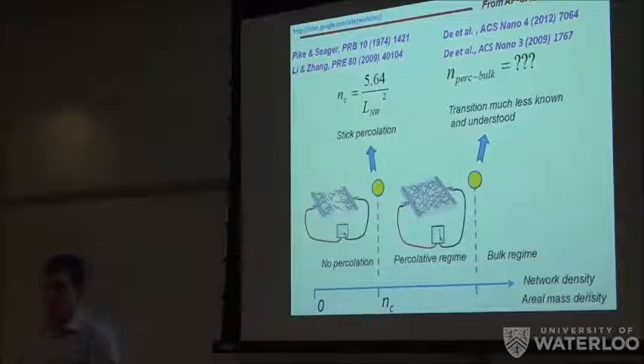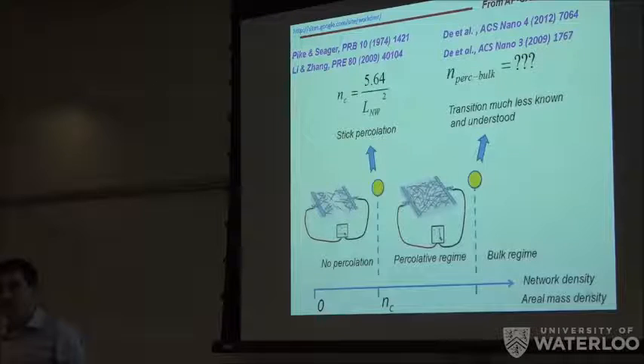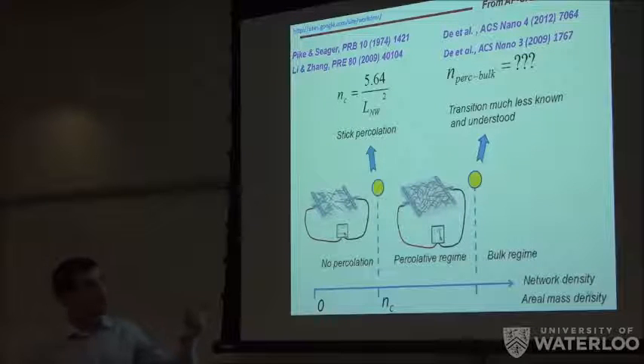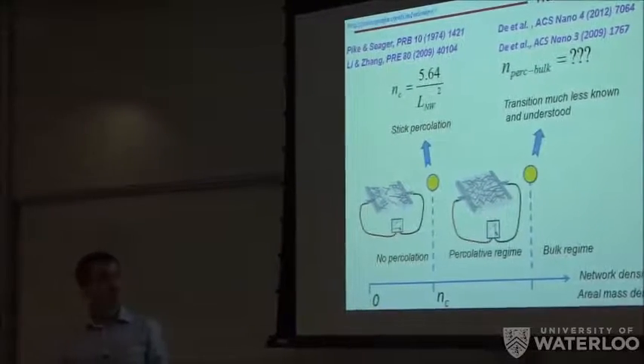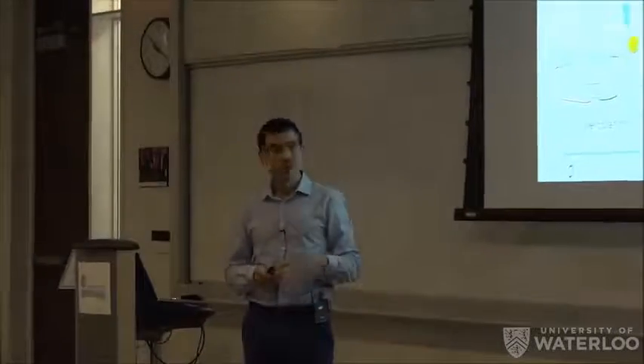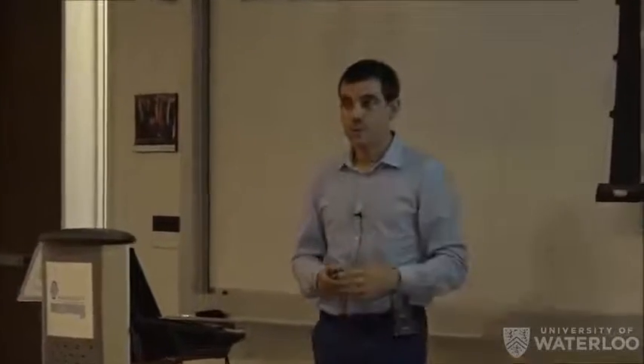Oh, I see. And did you heat the sample after coating? I'm showing electrical annealing. I don't have it here. I can look for it. Probably have it, but not in this presentation. But we also see an enhancement. I should have put it indeed because it's quite remarkable. We can go to almost 300 degrees, and the network is still stable.